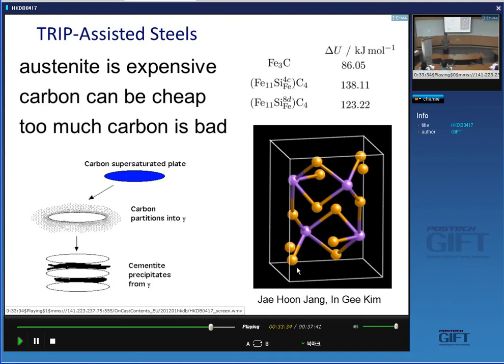cementite precipitation during the bainite reaction. So all you do is you take a steel, you transform it partly into bainite, that partitions carbon, and the carbon remains in the austenite and stabilizes the austenite. Yeah? So silicon doesn't dissolve in cementite, and that's the reason why cementite is suppressed. So you've got an incredibly cheap steel in which you retain austenite without adding expensive alloying additions.